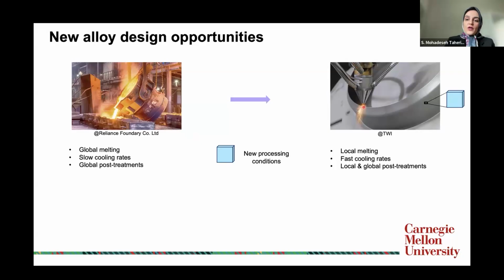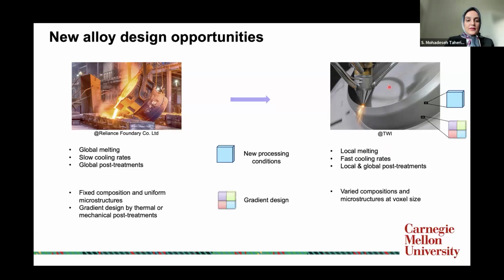Here, we just locally melt the added powder, and we have a fast cooling rate because of the laser interaction, and we also have the ability to locally do post-heat treatment.